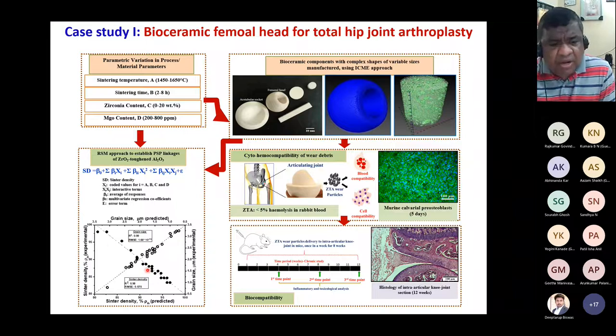And if you see the prediction capability of this response surface modeling approach, particularly in the context of this zirconia toughened alumina, it is very good because the R score and RMSE are very acceptable. Now, what is the beauty of this response surface modeling approach? The parameters that we optimized from this approach not only give us very dense components for the coupon samples, like 10 millimeter or 20 millimeter samples, but the same combination of sintering parameters was also utilized to fabricate femoral head and acetabular liner components.